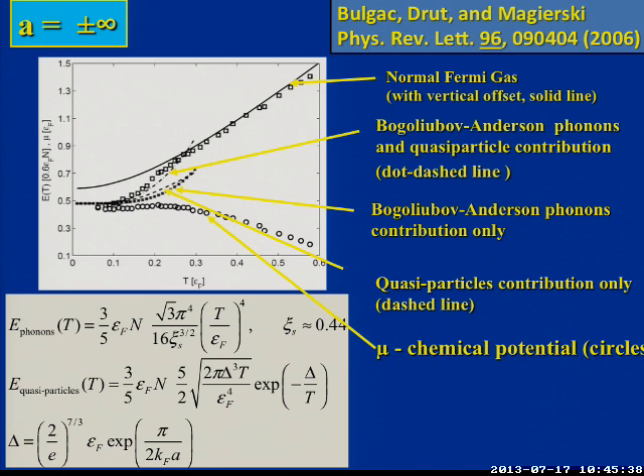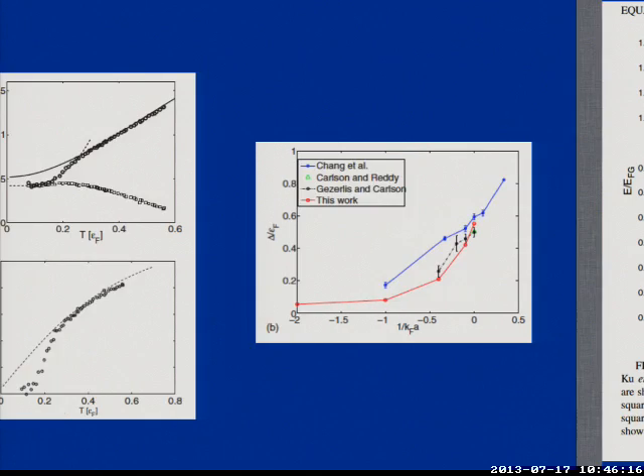And then the phonons, at the critical temperature, they don't exist anymore. So in principle this formula should exist somewhere here, but probably not today. So you can criticize this formula as much as you want, so don't put too much in it. The phonons are massless excitations, they're sound waves, and the quasi-particles, the broken pairs, require a mass gap, delta. So the two contributions are mutually exclusive. Either you have a mass gap or you don't. No, you have, I'll talk about the gap too. That's a separate discussion, it will be quite interesting too. Okay, so let's stop that for the moment.